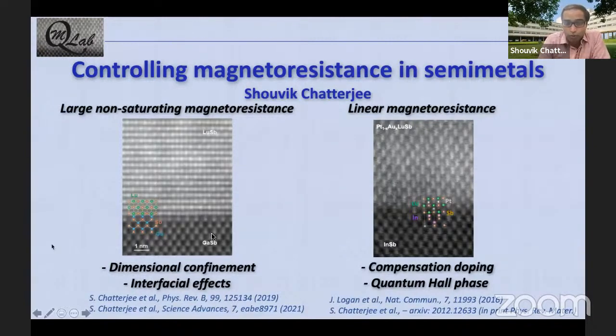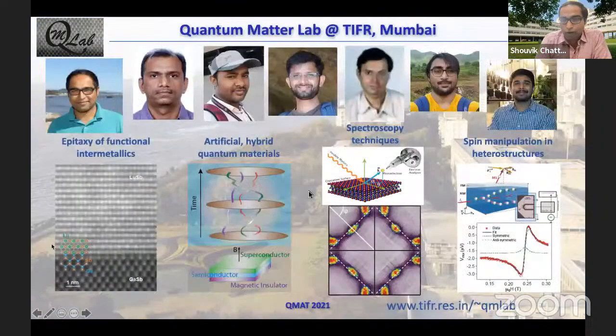And I'd try to show two different examples. One is that of lutetium antimony, the rare earth monopnictide, which shows a large non-saturating magnetoresistance. And if time permits, I'll also talk about topological states in a half-Heusler compound, platinum lutetium antimony, which shows a very strong linear magnetoresistance, and how we can control it and show the emergence of a quantum Hall-like phase.